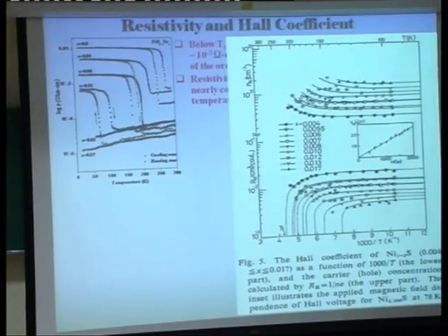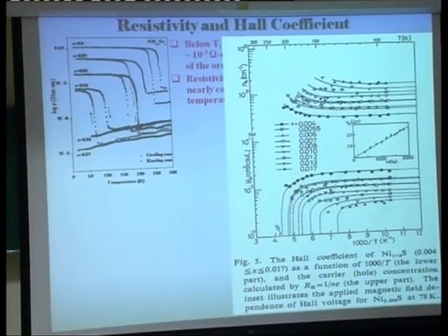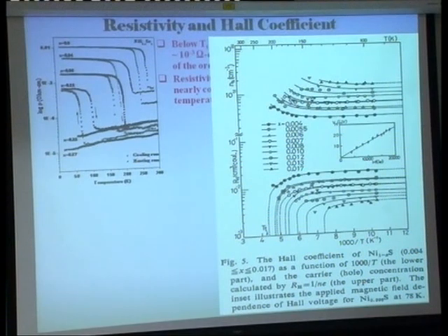So one can go and look at the Hall coefficient, because that can tell me the carrier concentration, and that's of course what one did. And here's the data for the Hall coefficient, the Hall carrier concentration. It's plotted over 1 over T.